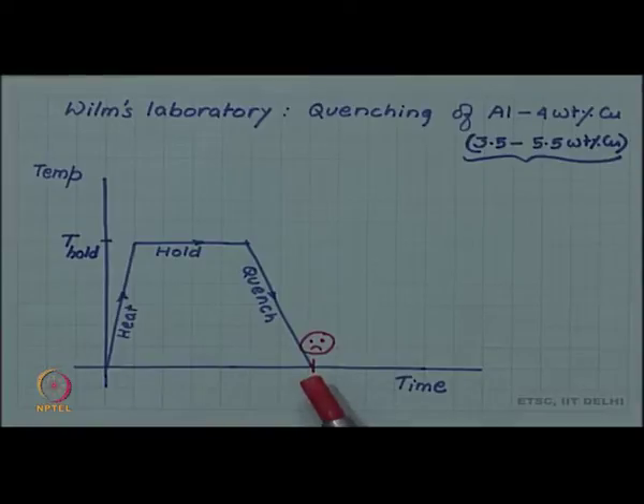And when he resumes, when he measures the hardness of the specimens which were quenched on Saturday but whose hardness was not measured, and he is measuring the hardness on Monday, he finds an increase in hardness. Hardness has actually increased.